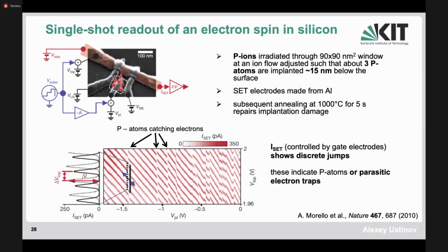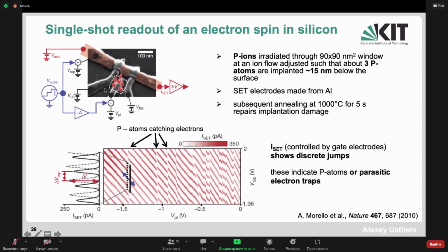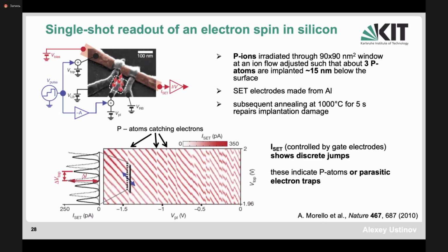So what they've done, they covered the silicon chip by a protection layer, and then irradiated the whole sample with high energy phosphorus ions. In this dashed rectangle, they had a small opening of about 90 times 90 nanometers. And according to the flux of phosphorus, they were expecting to have about 3 phosphorus ions in the small area. In the rest of the circuit, there were no phosphorus ions